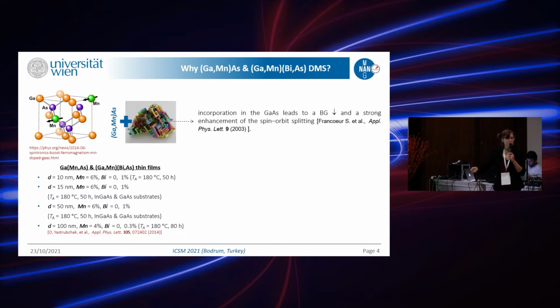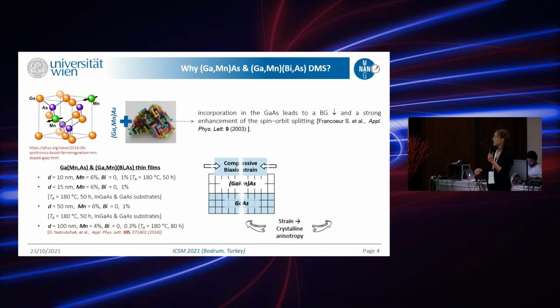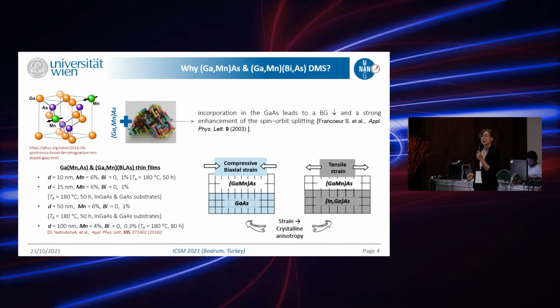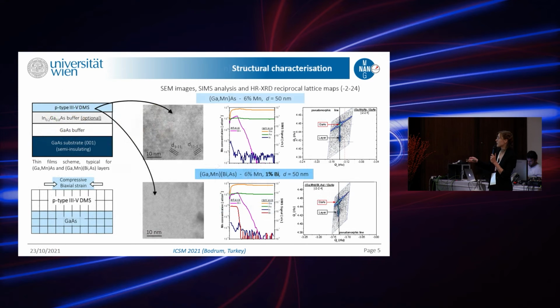Before proceeding further to characterization, I would like to briefly introduce what type of films we had. All the transport measurements were performed on 10 nanometer thick films with a manganese concentration of 6% and bismuth around 1%. Samples were grown by means of low-temperature molecular beam epitaxy on a gallium arsenide substrate. Hence, we have a compressive biaxial strain and in-plane anisotropy. We'll be working only with the compressive case, not with the tensile one, today.